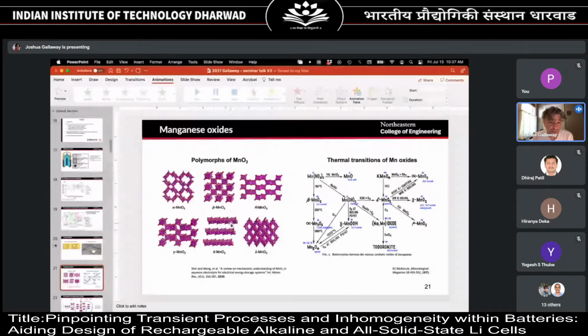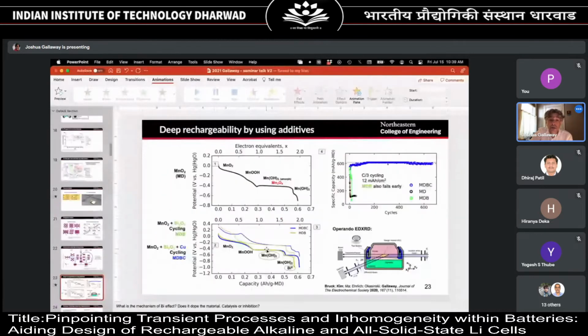Okay, so we've used our EDXRD technique to look at what's happening inside of the battery when we have the bismuth and copper additives in there. I showed before that on this part of the discharge curve, we got this material, Mn3O4, which makes the material non-rechargeable. But if we put the bismuth and copper additives in there, we do not get that material at the same part of the discharge curve. So the bismuth and copper additives, which make the MnO2 rechargeable, work because this material does not form, right? Now what we're trying to do is figure out why that is true. Why does the bismuth and copper cause that not to form?